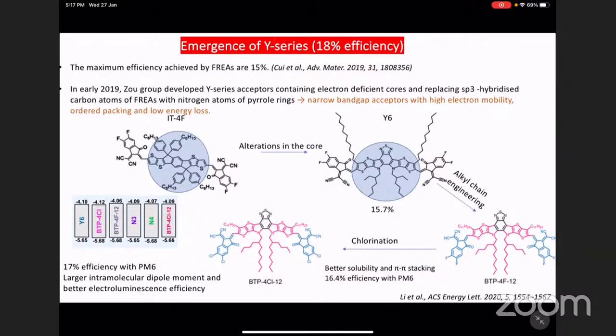After electronic level tuning, what Sudipto was asking, okay, how does the morphology look like? Alkyl chain engineering is required to have better packing, and then adding the chlorinations. Those have introduced some kind of twistings and dihedral angle change. The planarization of the chains could introduce lots of interesting properties, and we could see an overall improvement from 15.7 to 17%. It is a very good change, but how did it take place? We won't see much change in the VOC, but we'll see changes in the JSC and the fill factor.